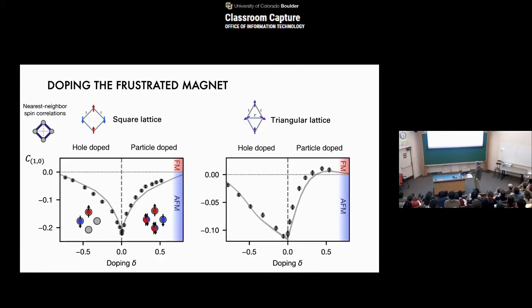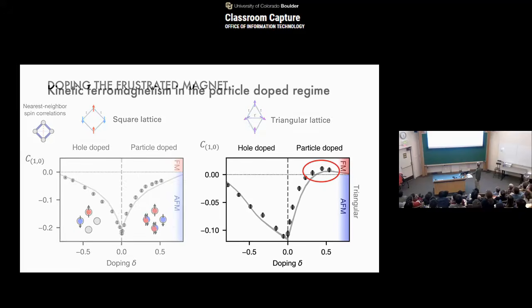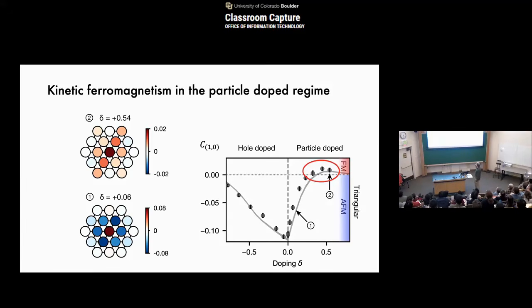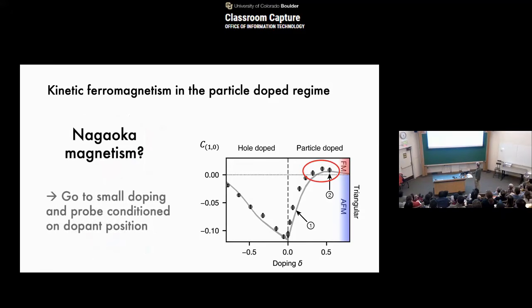And to our surprise, we found that if you dope a lot, if you have 50% more doublons here, then we actually saw that the nearest neighbor correlator turns ferromagnetic. And the question is, is this kinetic magnetism? Yeah, it seems like this is certainly going in the right direction. And so here again, you see that up here, all the spin-spin correlations turn ferromagnetic. But, well, it is kinetic magnetism, but it's very far away from this idea of Nagaoka, where he says one added particle turns the system ferromagnetic, right?